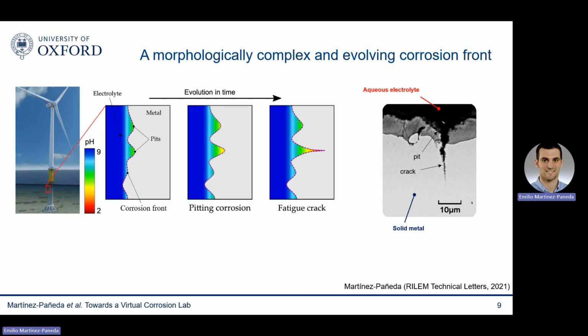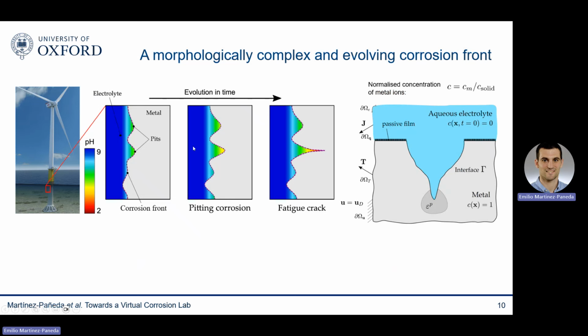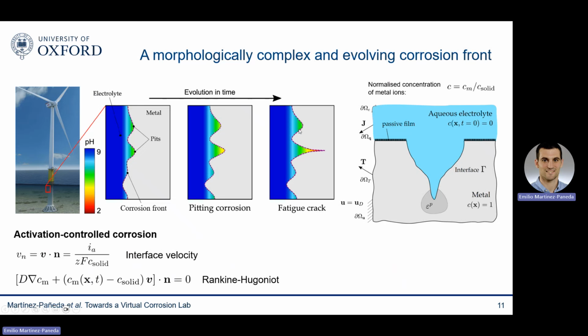You need to simulate the evolution of this interface, the corrosion front, and tracking the evolution of an evolving interface is a well-known mathematical and computational challenge. So let me show you this. If we think of the simplest way to mathematically express corrosion, we could define a normalized concentration of metal ions, which is equal to 1 in the metal and 0 far away from the corrosion front deep into the electrolyte. Then under conditions of activation control corrosion, the evolution of the interface velocity is given by Faraday's second law, and the concentration of metal ions in the interface is given by the Rankine-Hugoniot condition.